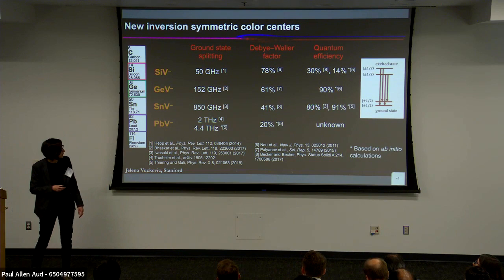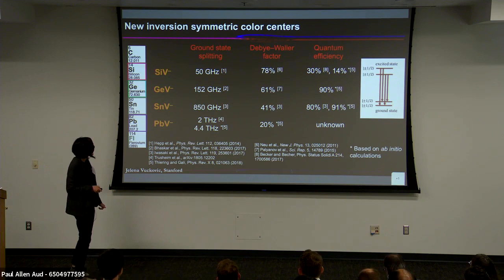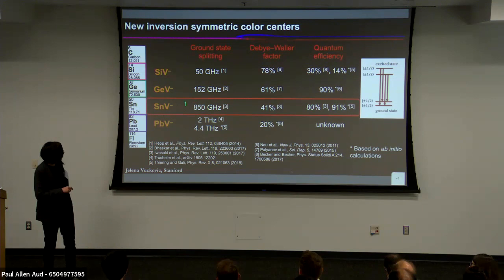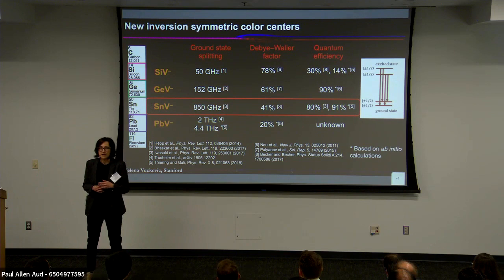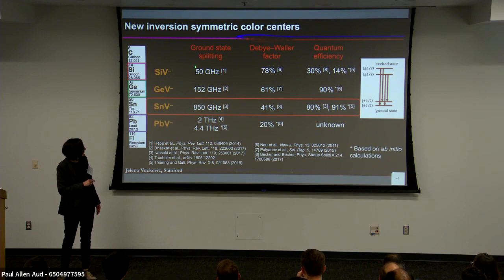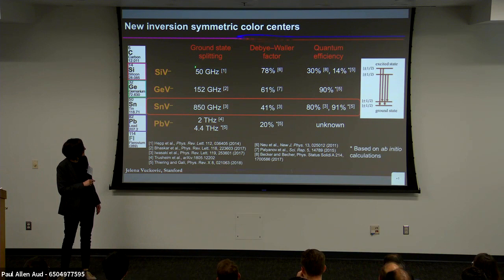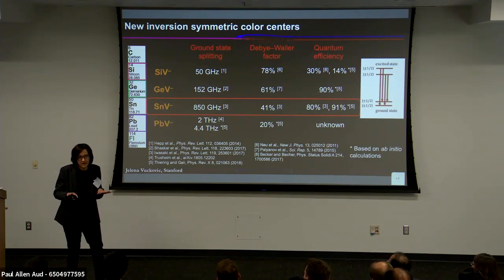We and others have been looking for systems that work at slightly elevated temperatures — for us, anything above 1.6 Kelvin is great, as it doesn't increase experimental complexity. We've been looking at this group of color centers, and the one we're particularly excited about is tin vacancy. All of them have exactly the same geometry as silicon vacancy — inversion symmetric and immune to static electric fields — so you can embed them in structures without degradation. Tin vacancy has a much larger ground state splitting: 850 gigahertz, compared to 50 gigahertz for silicon vacancy, which means at few-Kelvin temperatures you should see the same electron spin coherence as silicon vacancy in a dilution refrigerator.